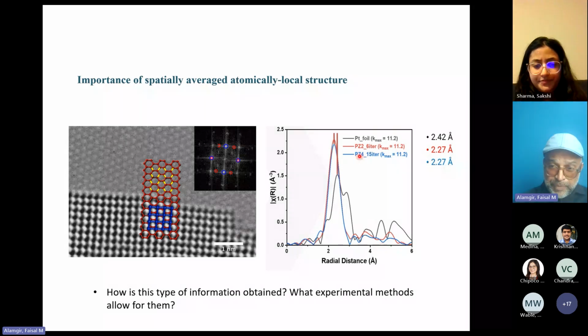So what's the point of this distribution? The point here is that when we compare our atomically thin platinum on the graphene to bulk platinum, that is platinum foil, which is in black here, you can see that there is a compression. That is, the first nearest neighbor is at a shorter distance in the case of this atomically thin metal film compared to the bulk. This compression is real. You can see that the average, which is giving you a distribution here, the average position is now shifted down compared to the average position in the platinum foil.